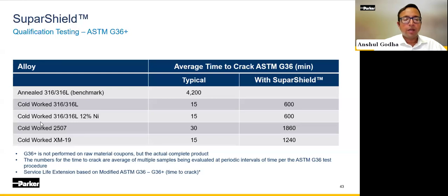So what does this mean practically? I shared with you earlier a table where we talked about the performance of the different cold worked alloys and how quickly they would tend to crack under the ASTM G36 conditions. After Super Shield, the improvement in performance is quite dramatic across the board, even on cold worked alloys. This is important because this enables us to use cold worked alloys, especially 316, and still get remarkable performance, often comparable to higher alloyed options that are currently out there.